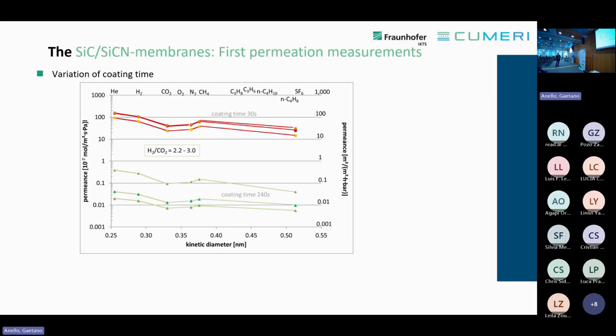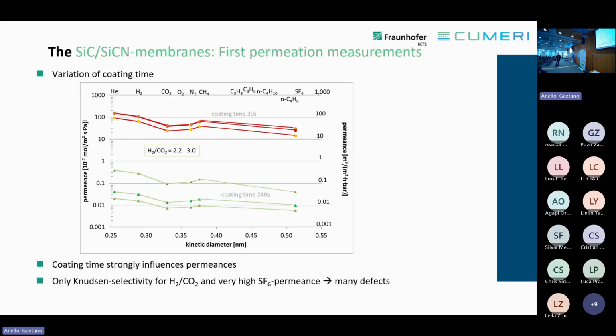If we are coating for a long time, we get very low permeances. However, we can also see that the ideal perm-selectivity of hydrogen over CO2 is only in the range of Knudsen, 2.2 to 3. We can also see that the SF6 permeance, the biggest molecule, is still quite high, so we have a lot of leaks. So all in all, there is a lot left to do.